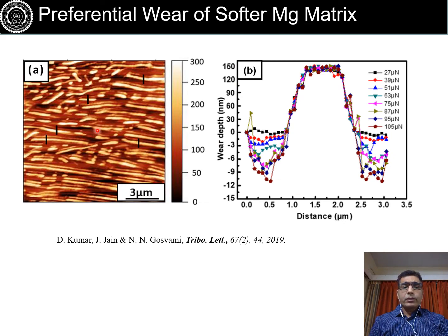We also saw some interesting wear behavior of these fine precipitate containing regions. We tracked wear around a single precipitate, and we see that the precipitate does not wear, as a function of sliding tests at different loads. We can continuously slide, then change the load and slide again. In multiple sliding experiments conducted in a single region, the precipitate has not worn at all, whereas the matrix is continuously getting worn out as a function of time. So some wear is happening despite these precipitates not wearing at all.